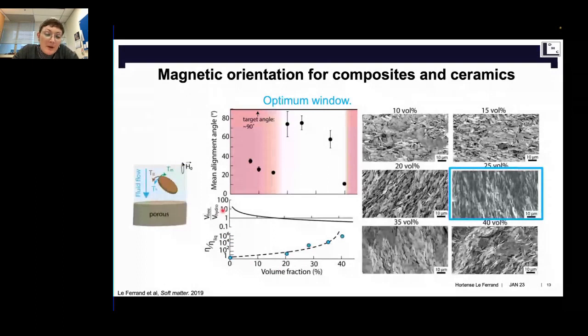So what these graphs show is that if you have low volume fraction, the platelets have a lot of free space to move around, but you cannot really align them as you want because of forces such as gravity or any hydrodynamic flow that will put the platelets down. If in turn you are too concentrated, there is very little possibility for the particles to rotate and align themselves. And at the end of the day, you cannot align. So there is an optimum window of concentration to allow this orientation to be retained, especially after drying the material.